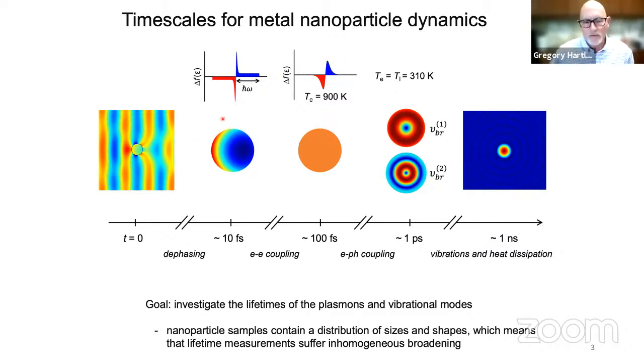Okay, and that dephasing process creates hot electrons in the metal nanostructure. And those electrons are distributed in space in a way that depends on the internal electric fields in the structure. And they're distributed over a fairly wide range of energy after that initial absorption of a photon. Okay, so these hot electrons, which are currently of a lot of interest in photocatalysis, they interact amongst themselves and redistribute this energy to create a Fermi distribution at some high temperature. And so that process is this electron-electron coupling, and that happens in about 100 femtoseconds, so about 10 times slower than this initial dephasing of the plasmon.